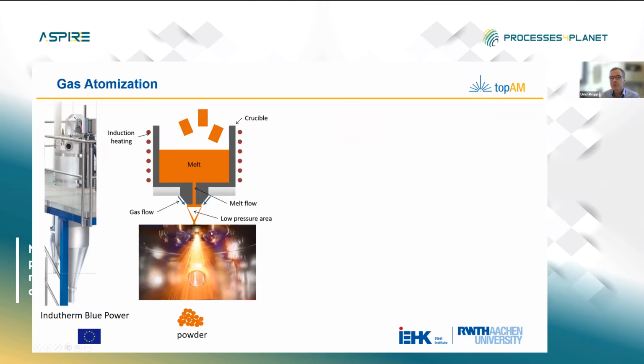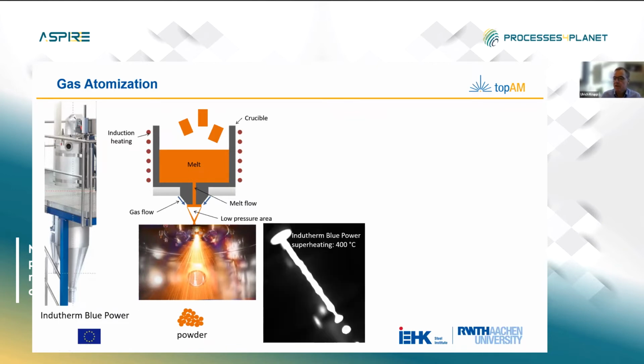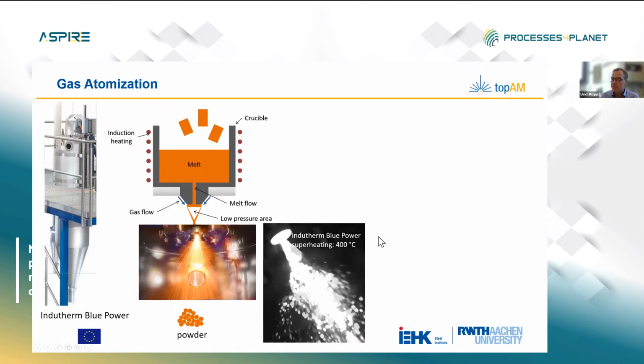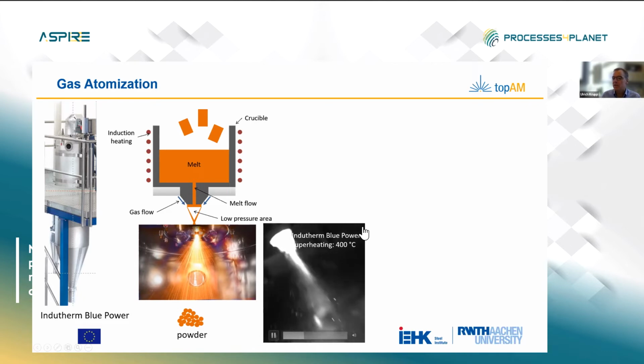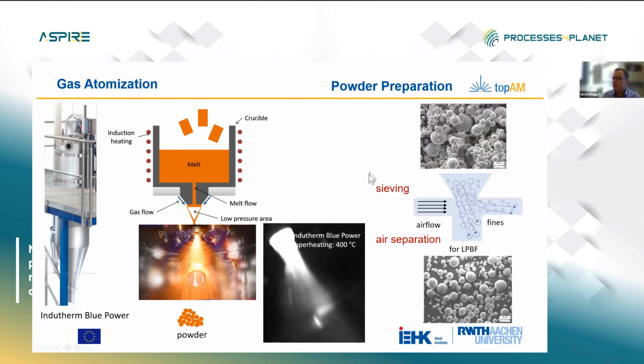Let me start to introduce the gas atomization process. Here the alloy is molten in an induction furnace, and then by high pressure argon, the melt is sprayed into a large stainless steel vessel, and the solidified droplets later become the powder that can be seen here. That is a high-speed camera. Here the atomization starts, and you see the droplets which then solidify and become the powder. The raw powder then has to be prepared by sieving out the coarse powder particles, and then we use air separation to get rid of the powder fines. That is a suitable powder for laser powder bed fusion.